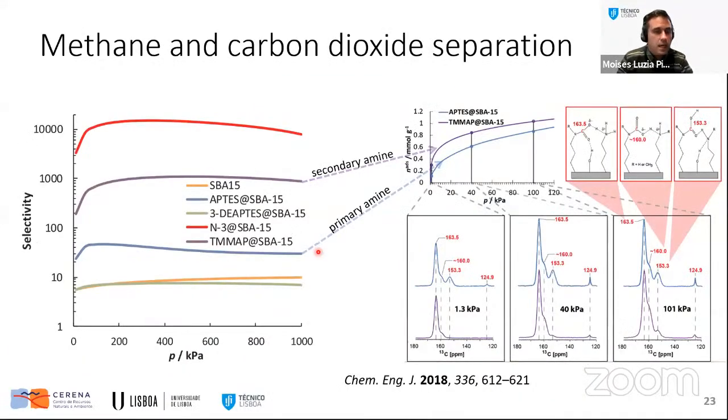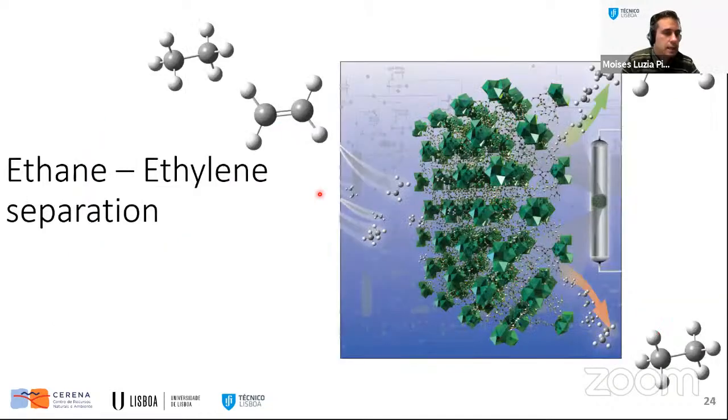So going back to adsorption and selectivity, we can see in here a very high increase of several orders of magnitude, because it really steeps at very low pressures. And this can be related to the formation of the species with pressure. So we can correlate the increase of the amount adsorbed with the species that are being formed at the surface. These are formed at very low pressures first, and then we move on to the other ones after.